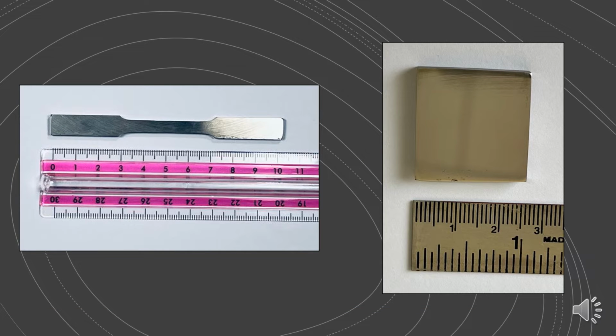In order to perform the experiments, all the 4 steels were cut according to ASTM E8M standards for doing tensile tests. 3 specimens were made for each test condition. Also, a 25 mm by 25 mm section was cut in order to perform hardness tests at different aging durations.